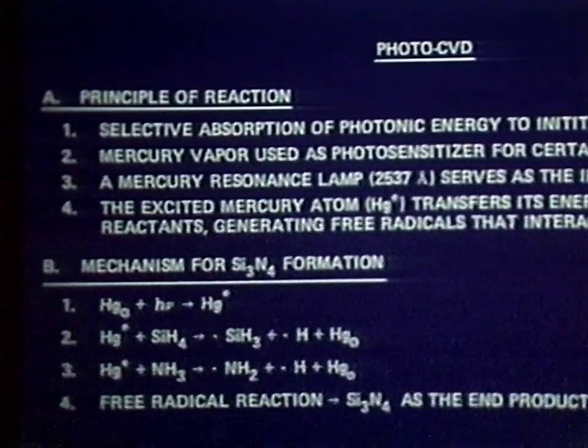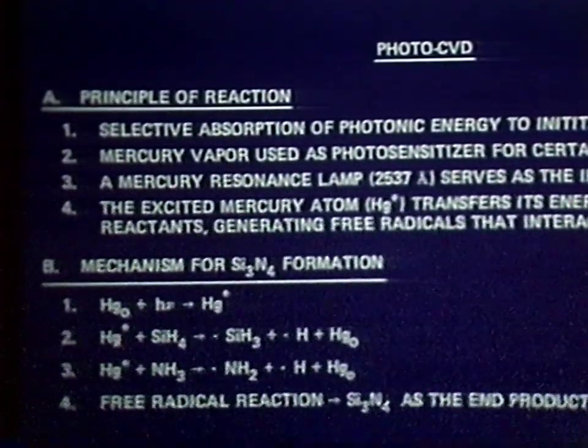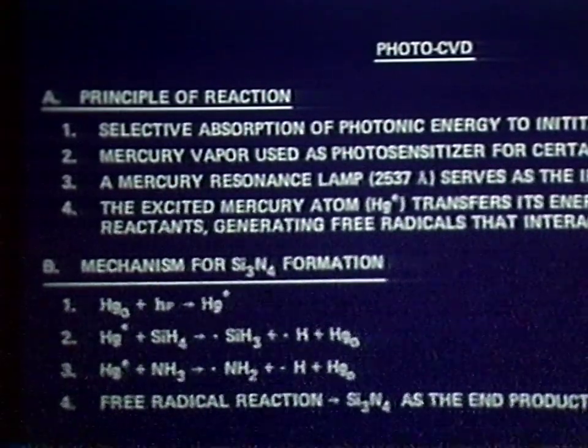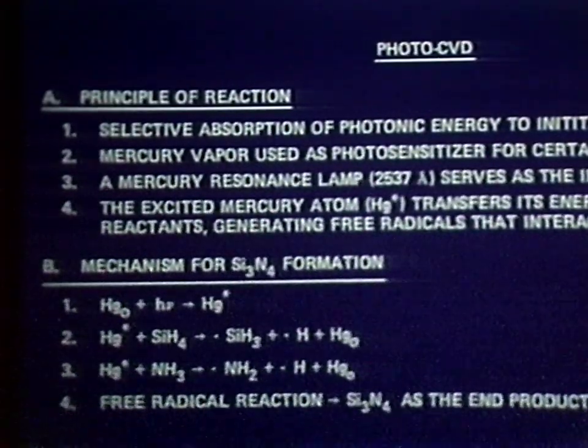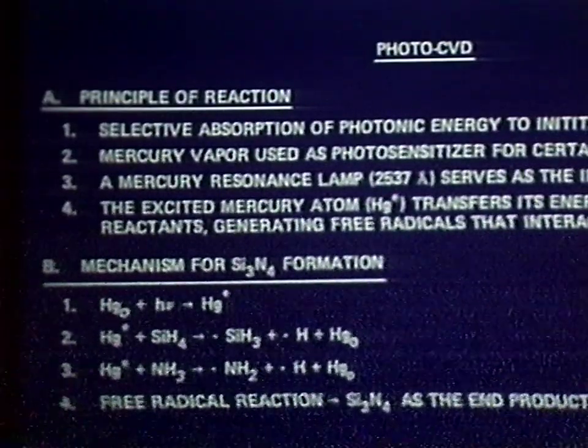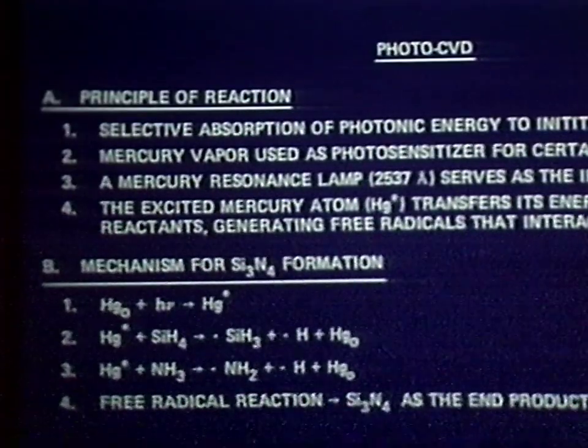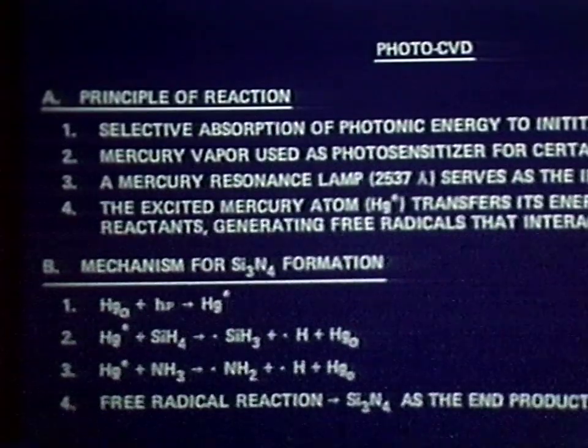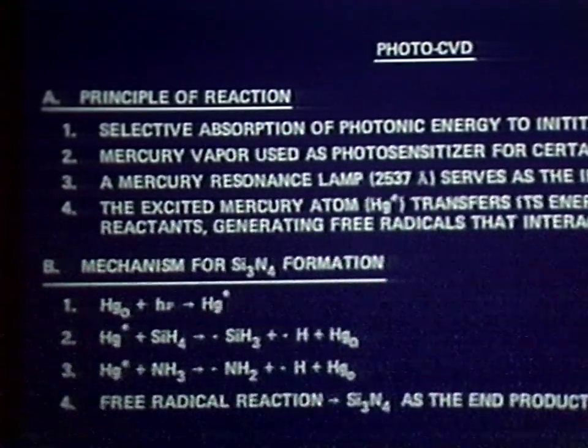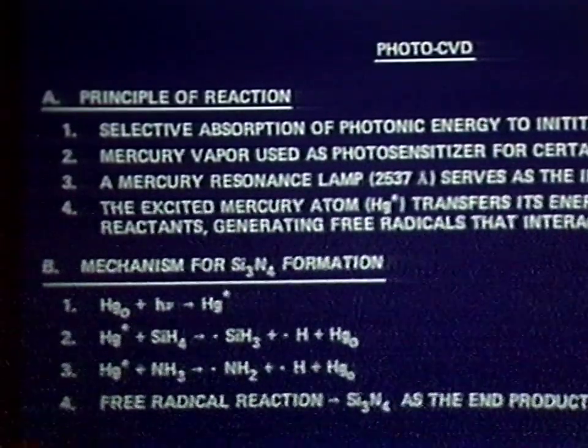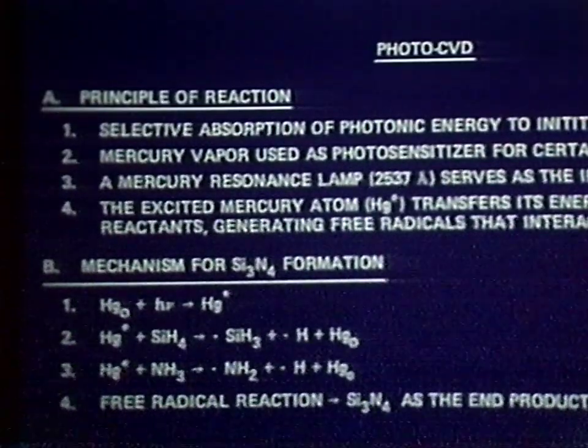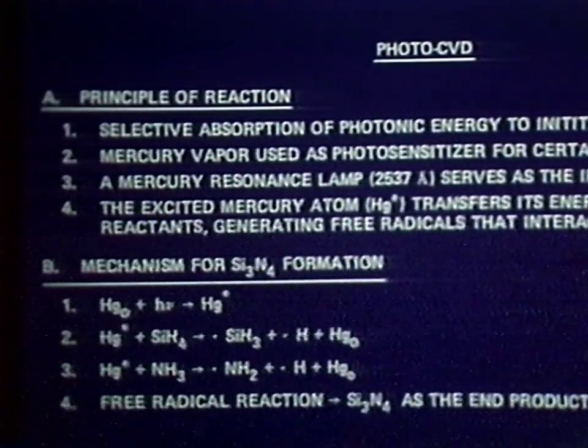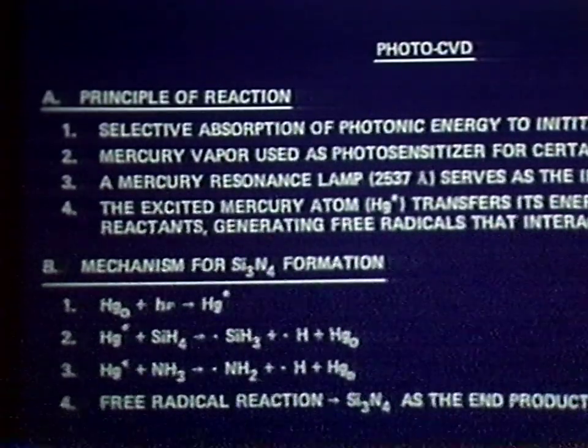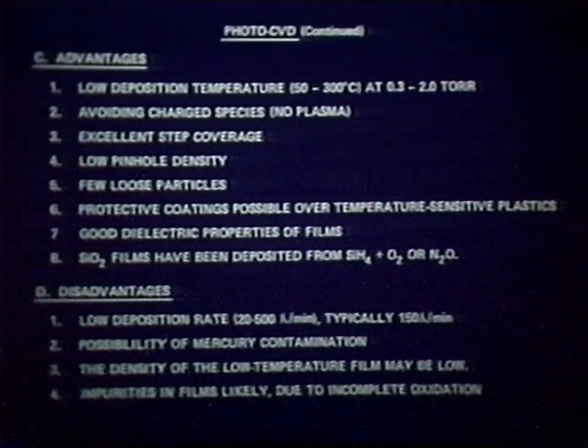Very simply listed here is the formation of species that will produce silicon nitride. We have mercury in the ground state being activated to excited mercury, which then interacts with silane to produce a silyl radical and a hydrogen radical, and it goes back to mercury in the ground state. In other words, the mercury really acts as a catalyst, which is not consumed, it's regenerated. And again, down here, the mercury will again be activated and produce a radical with ammonia, an ammonia-type radical, going back to the ground state. And the various species now, of course, interact, finally forming silicon nitride. Of course, there are many more steps involved in that type of reaction, but which are quite poorly understood at this time.